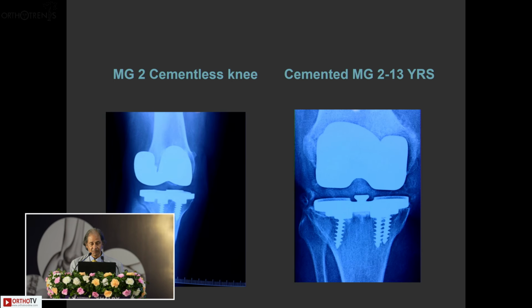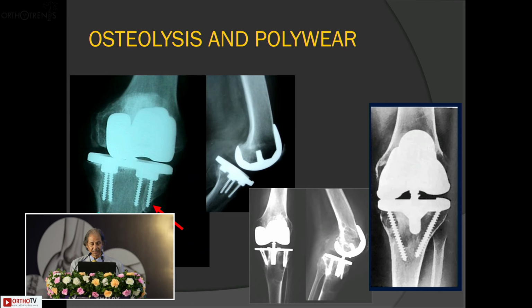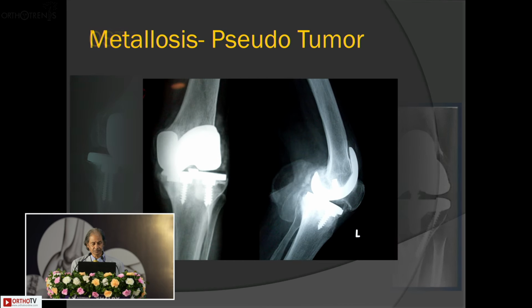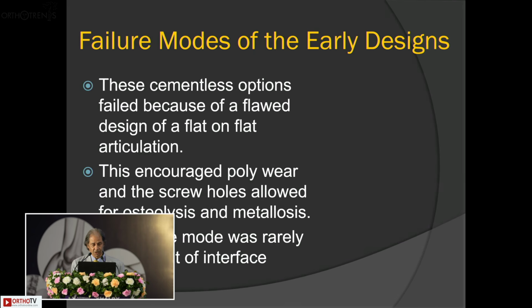This again was some long-term outcomes at 13 years. But then this started to happen. We started to see osteolysis and polyethylene wear. And the formation of these pseudotumors and osteolysis. These were pretty catastrophic failures.